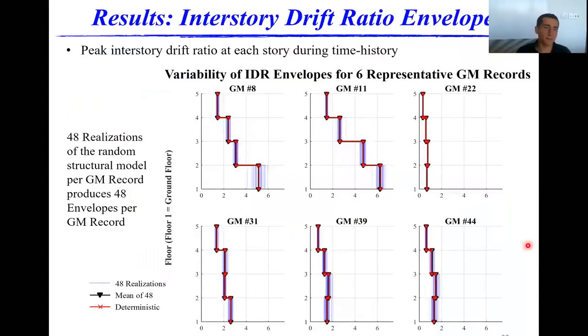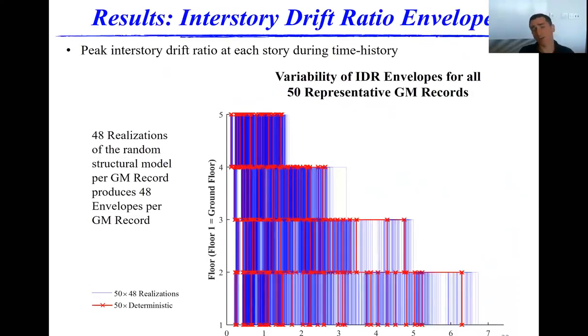I did the same thing with the peak interstory drift ratio. At each story, I selected 6 representative ground motion records, a few that have almost no sensitivity to model parameter uncertainty, others where on one floor you see a range from 4 to 6%, so that's not negligible by anyone's standards. And so now we can also look at all 2,400 realizations of the interstory drift ratio envelopes compared to the 50 deterministic envelopes. And again, we see that they cover the same scatter.